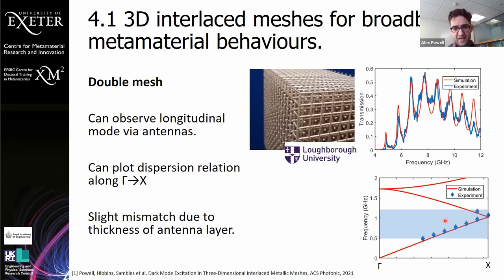There's a slight offset here, which is due to the fact that this band structure is calculated simulating an infinite material in three dimensions. And we actually do have a small but finite thickness from this matching layer where the antennas are, which offsets everything very slightly.